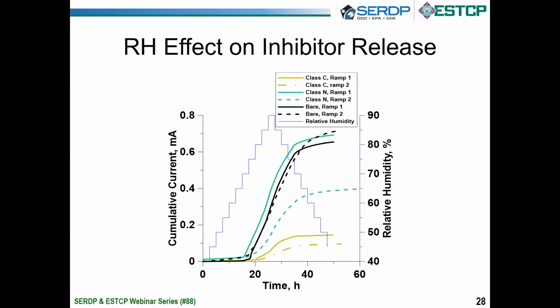So the chromate coating under the same conditions is here, this gold curve, and you can see the big knockdown factor. Now, if you're a manufacturer of the non-chrome coating and you looked at this data, you'd be pretty disappointed because you would say, oh my gosh, this is as bad. And if you didn't care about statistics, you would say, oh my gosh, this is worse. But basically for the purpose of this talk, we'll say it looks like nothing's happening.